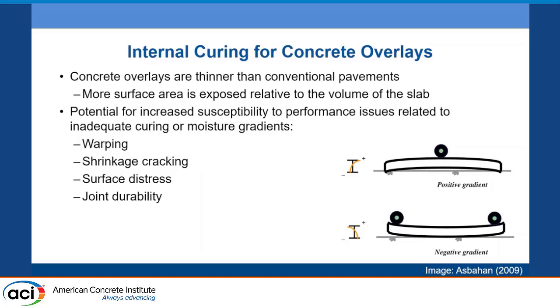It can also induce additional stresses and potentially reduce the fatigue life of the slab if you do have a significant amount of warping. And obviously, the temperature gradient plays a role in this as well, and sometimes they're lumped together, and you'll see curling and warping used interchangeably. But the moisture gradient plays a significant role in that process, and that's obviously in addition to the potential for shrinkage cracking, especially if we're in dry conditions and the pavement isn't well cured. And again, just susceptibility to other types of surface stresses and potential for joint deterioration related issues.